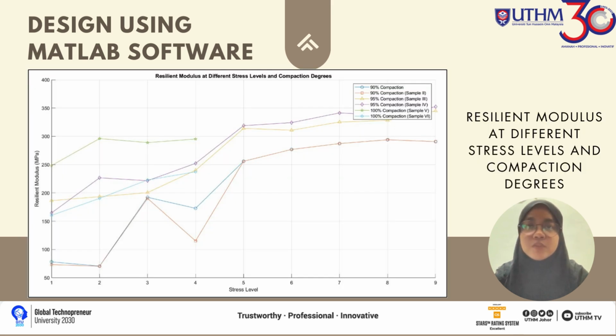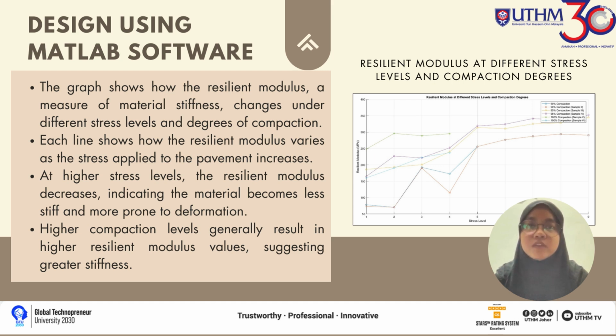Resilient modulus at different stress levels and compaction degrees. The graph shows how the resilient modulus, a measure of material stiffness, changes under different stress levels and degrees of compaction. Each line shows how the resilient modulus varies as the stress applied to the pavement increases. For instance, at higher stress levels, the resilient modulus tends to decrease, indicating the material becomes less stiff and more prone to deformation. Higher compaction levels generally result in higher resilient modulus values, suggesting greater stiffness and better resistance to deformation.